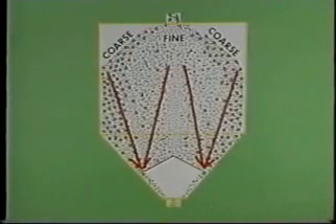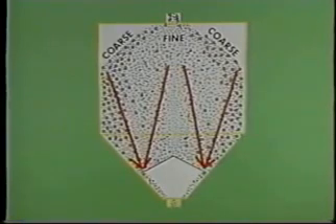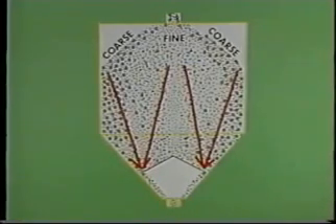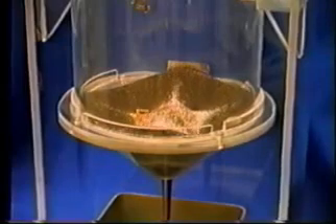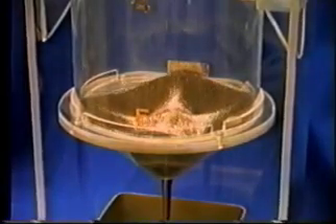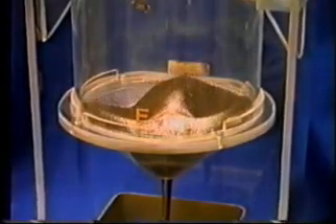The arrows on this illustration indicate how the sand is feeding to these openings in the inverted cone. The coarse grains on the outside are blending with the fine grains on the inside, as well as the intermediate grains which are halfway across the radius of the bin and exiting through the openings in the inverted cone. Since the area of discharge is larger than the sum of the four openings in the cone, the sand is mixed together at the discharge.